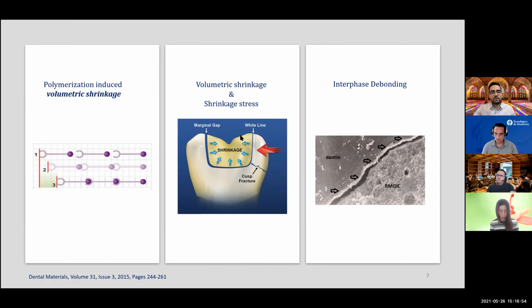So imagine that we have a tooth cavity and we want to put some material in it. During the photopolymerization, some volumetric shrinkage can happen, and first of all, maybe we have some marginal gap in the bonding of the restorative material, the material that we want to use for filling the tooth structure. And we have the marginal gap here, or interface debonding, and at the same time, because this shrinkage strain can happen under confinement, some stress can be generated, and it's known as shrinkage stress.